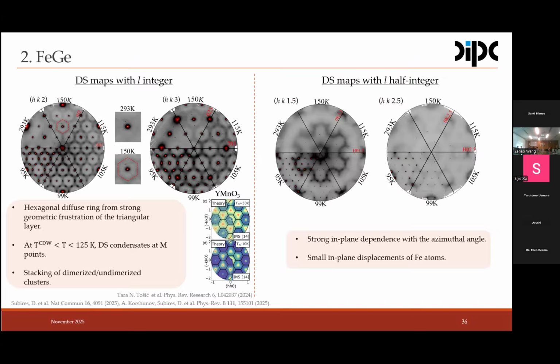So this hexagonal diffuse scattering actually is a hallmark of strong geometrical frustration. It's widely reported in magnetic materials in hexagonal lattices, antiferromagnetic hexagonal lattices, which at high temperatures above the Néel transition develop a hexagonal diffuse signal, right? And this is a consequence of the strong magnetic frustration.